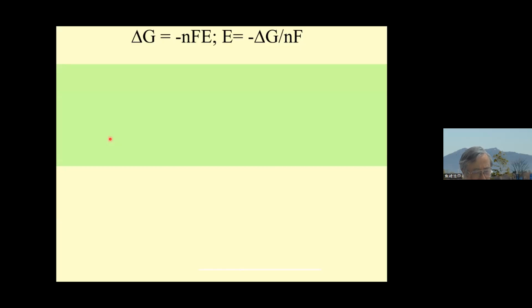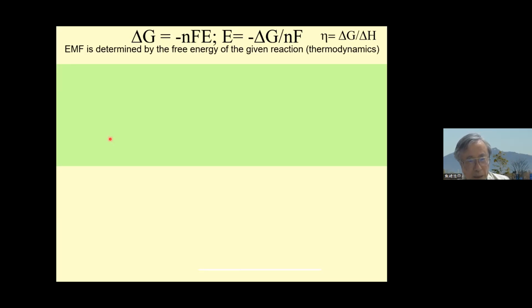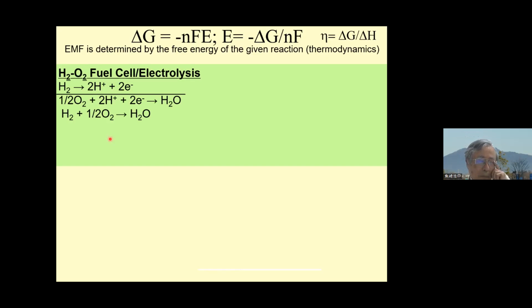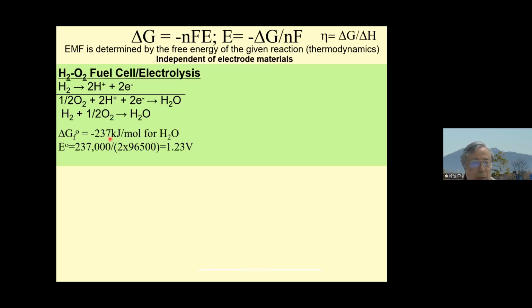Now, this is, of course, an important equation for electrochemical energy conversion. The electromotive force is determined by the free energy of the given reaction. So thermodynamics determines this voltage generation. Because this is a direct energy conversion without thermal to mechanical conversion, the theoretical efficiency is relatively high. For example, the hydrogen-oxygen fuel cell, or electrolysis, which is the reverse reaction of the fuel cell. This is actually the formation or decomposition of water from hydrogen and oxygen. So you can calculate the free energy of formation, and then the theoretical electromotive force is 1.23 volt. So in this equation, no electrode materials are involved, so this electromotive force is independent of electrode materials.